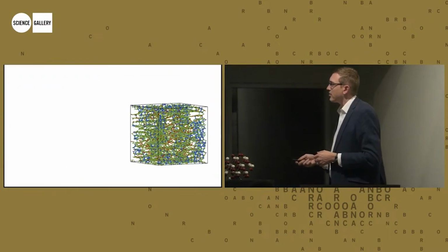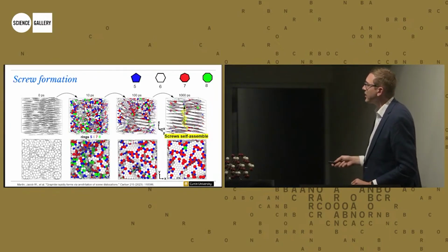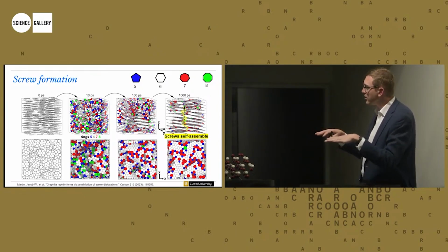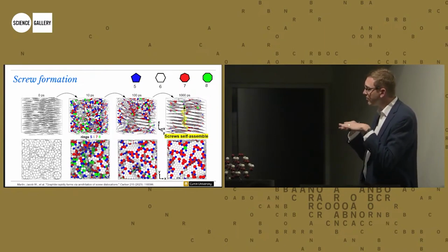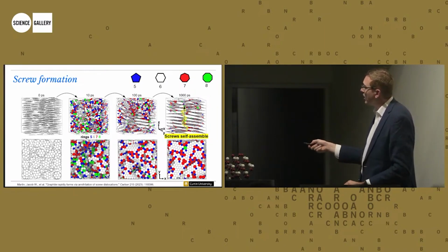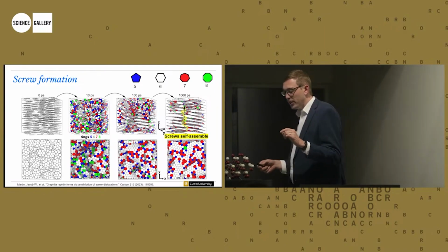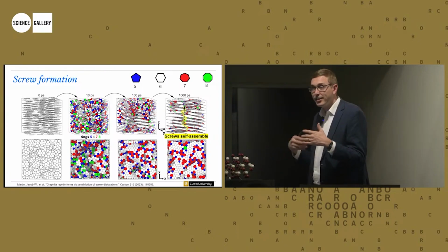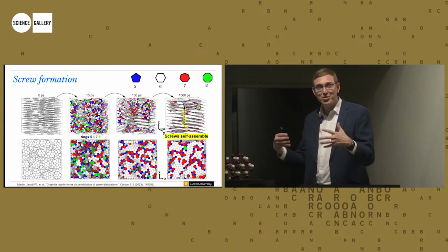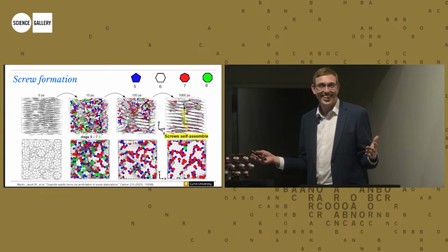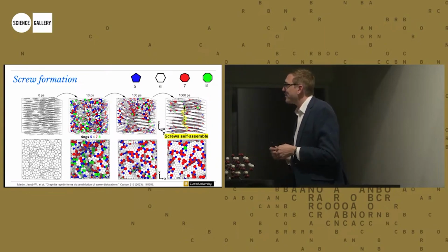So another way to look at this is we can look at the different rings and we can color them according to cycle number. And we see, this is quite useful because it sort of sees the carbon, the graphene sheets like an actual mesh. And you can see a screw going up through that structure, okay? But this is something we couldn't do in the experiment. We could actually keep playing the video. We could keep the simulation going. How do they go away? And so that's what we did.